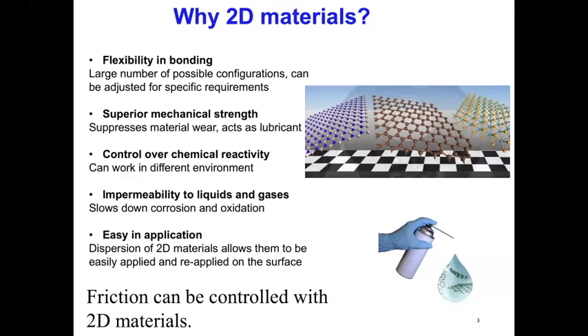characteristics of the materials with sliding, like rubbing in different mechanical systems. And then why we actually started this whole work: we started to look for a solution of how we can easily apply these materials to the sliding surfaces. Specifically, we looked at one way of dispersing the two-dimensional materials in a carrier solution, which can be easily applied on the surfaces and then reapplied upon wear when we need to replenish our coating.